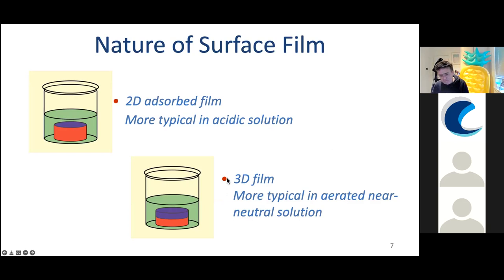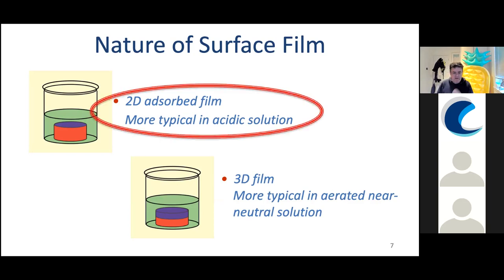You get thicker films commonly, 3D films. They can be a number of nanometers thick, up to microns in some cases, and they're more typically found in aerated near neutral solutions. What I'm going to focus on this evening is the work we've done in this area on 2D films in acidic solutions.